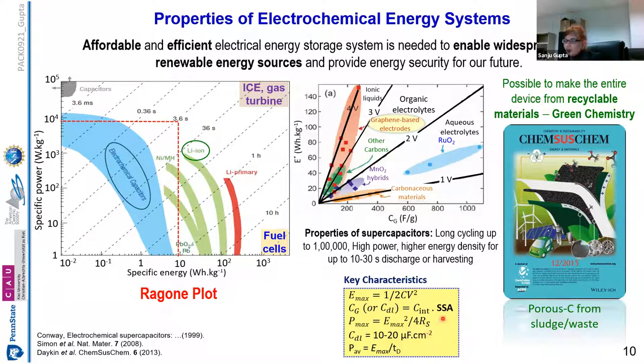And as I mentioned, it is not just the geometric area, but the specific surface area. Likewise, to increase the power density, we increase the energy density or decrease what we call the solution resistance, which we are talking about in milliohms or a couple of tens of milliohms. The other way to assess the average power is through the maximum energy divided by the TD, which is nothing but the discharge time, depending upon the mode of measurement.